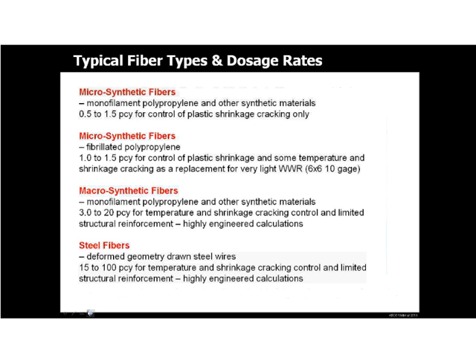From an application standpoint, this is falling in line with some of the material you've already seen. The use of microfibers, again at 1 to 1.5 pounds per yard. You can make an argument that some of these fibers might go as far as controlling some temperature and shrinkage cracking for light welded wire reinforcing. But if you wish to replace steel, and I'm going to focus a little bit on that later in this presentation, you do need to convert or upgrade to the macrosynthetics and the steel fiber products.